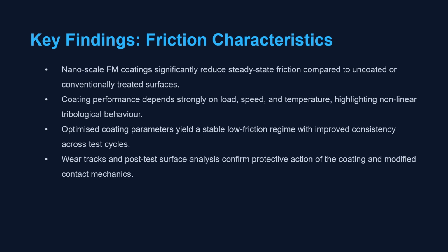Third, post-test wear analysis revealed the protective mechanism. The solid lubricant coating transfers a protective film to the counterface, reducing direct metal-on-metal contact and subsurface damage. This is the fundamental advantage of solid lubrication. It sacrifices a tiny amount of coating to protect the underlying rail steel from rolling contact fatigue. This solid lubrication approach is especially suited to railways because it's durable, predictable, and doesn't depend on liquid film continuity.